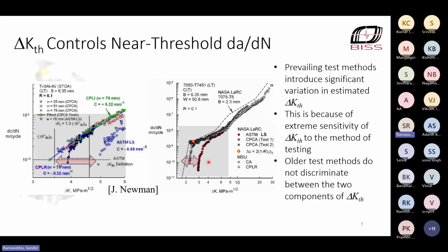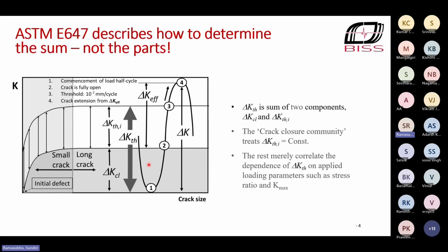So in any case, the story is that the delta K threshold is very sensitive to how you measure it. But there is a more important thing, and that is that delta K threshold actually consists of two parts.